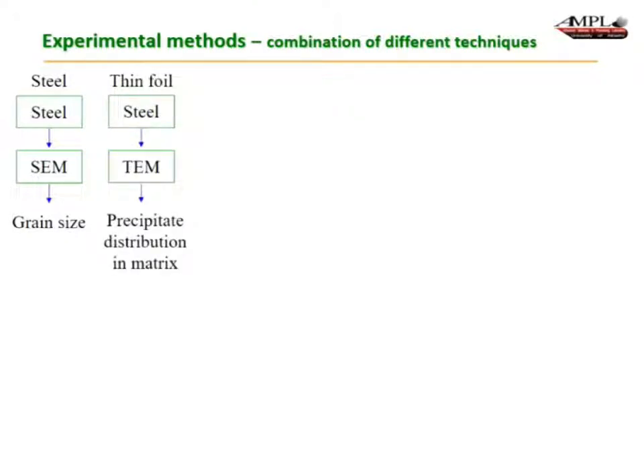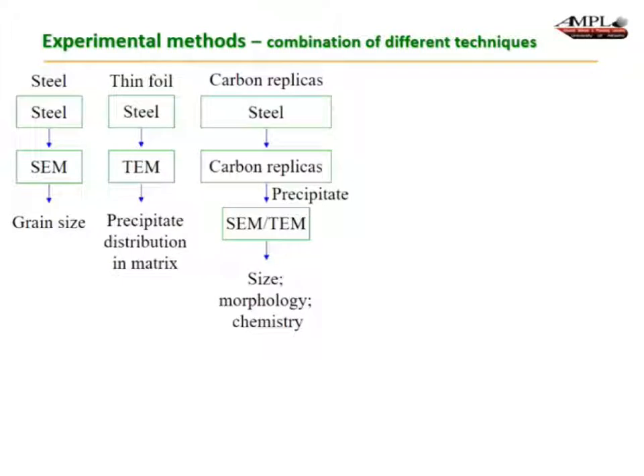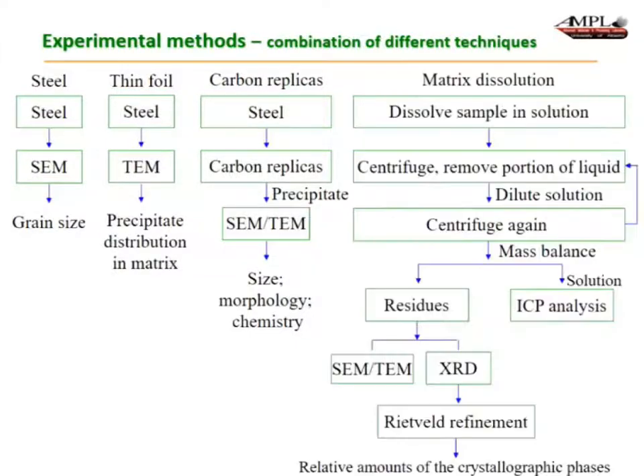Okay, so what was the method that was used? First thing, if you have a sample of steel, you can put it in the SEM and you can get grain size. And that's a quantitative measure. You can make a thin foil out of it and do a TEM and get a precipitate distribution in the matrix. But that's not really quantitative because you don't know what the size of the sample is, and the sample for TEM is rather small. If you do a carbon replica, again, you can get the size and the morphology and the chemistry, but the sample size is small, and the volume of the steel from which the precipitates come from is unknown, really. There's too much error associated with it.